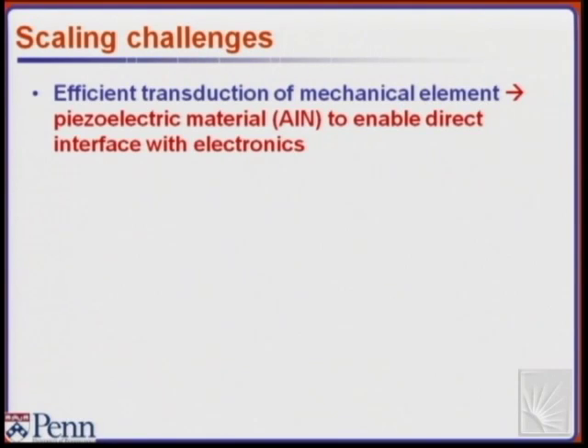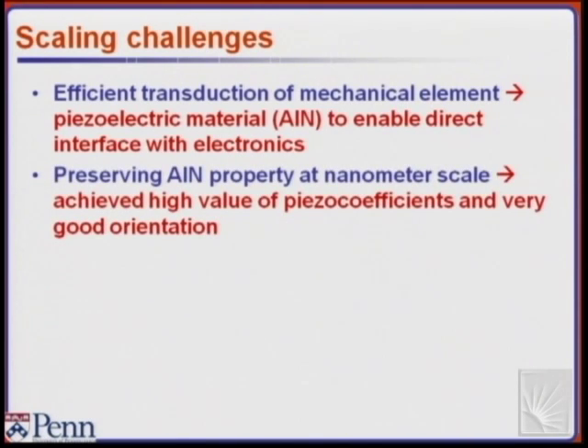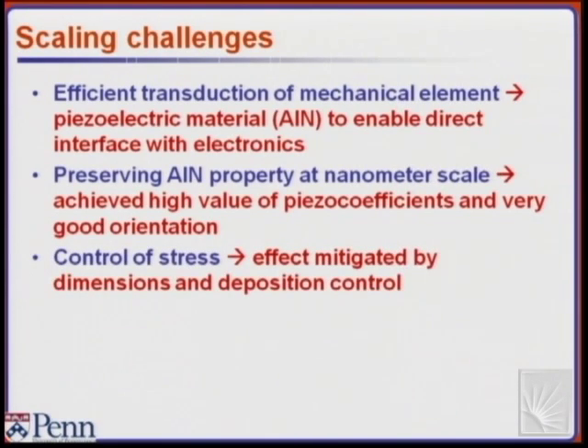So I'll try to summarize the fact that this scaling comes with challenges, and then I'll go over these challenges while I talk about the different devices and how we address them. The first thing, which I think I already clarified, was the selection of an effective and efficient transduction mechanism: piezoelectric as the efficient mechanism over electrostatic or thermal, and aluminum nitride as the material of choice. Then the problem is preserving the aluminum nitride properties at the nanometer scale. I will show you some results at 250 nanometers for resonators and 100 nanometers for mechanical switches, where we were able to preserve good orientation, and even scaling to 50 nanometers for some of these switches, for which we don't have experimental results yet, but the preliminary data on film deposition are very promising. So there's a continuous path for miniaturization. Stress is another problem that people working with IC and CMOS generally neglect, and it's extremely important instead for miniaturized structures because it plays a key role for moving structures.